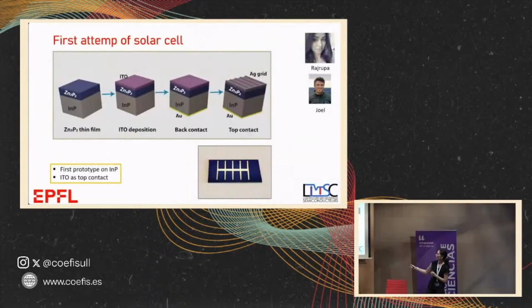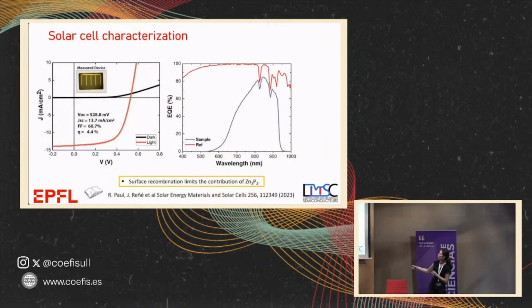So we created this device, and this is an example with the zinc phosphide. We put the indium tin oxide as a transparent electrode. It's a material that conducts, but it's transparent. We put some metal to extract the current, and then we measure. And what you see here, this current voltage curve, is typical of a diode.